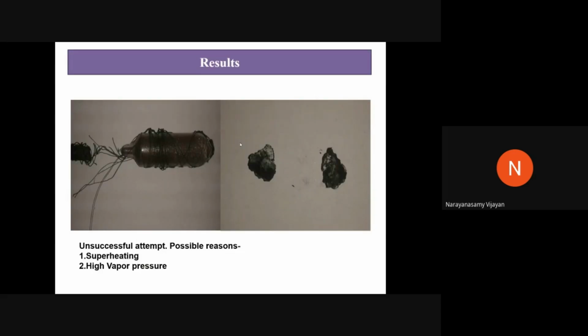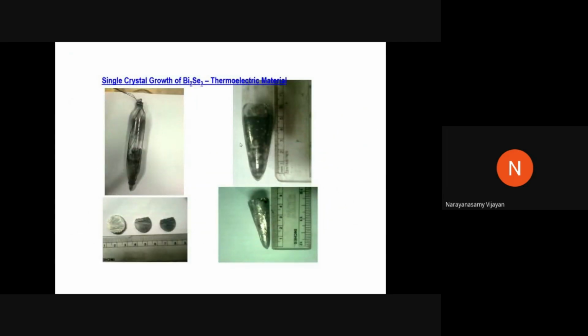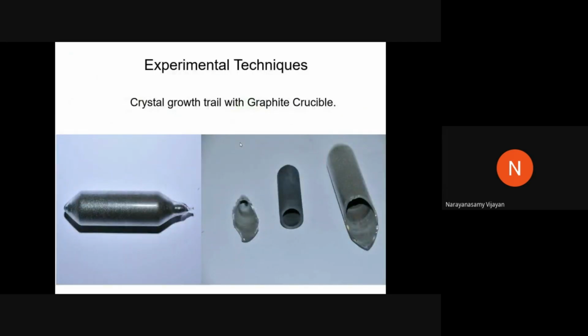And you can see here, some of the initial experiments were failures. After that, we changed some of the temperature profile, and finally we successfully grew the magnesium disilicide single crystal and the bismuth selenide single crystal. You can see some of the crystals we have grown.